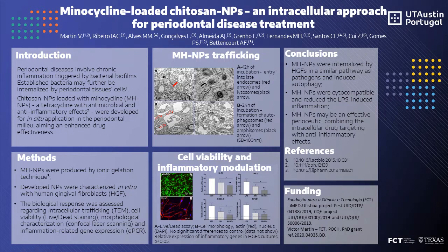Regarding the uptake and intracellular trafficking, nanoparticles enter in the cells via macropinocytosis and endocytosis. After 12 hours, nanoparticles were found inside endosomes and lysosomes, and the number of vesicles was increased in comparison to control. Then, after 24 hours of incubation, we can see autophagosomes and amphisomes, the fusion of endosomes, suggesting an autophagy induction. The cellular trafficking is the same as P. gingivalis, one of the main periodontal pathogens.